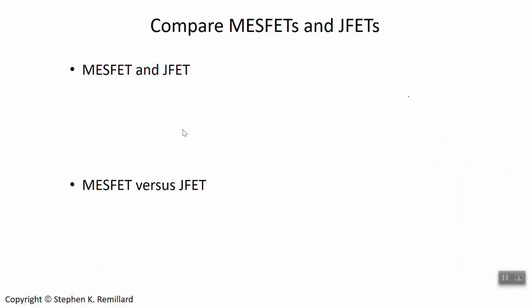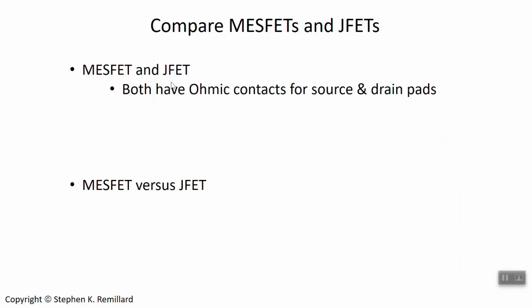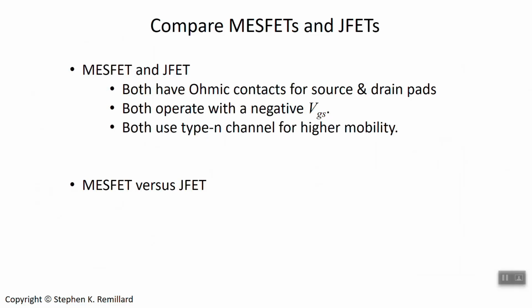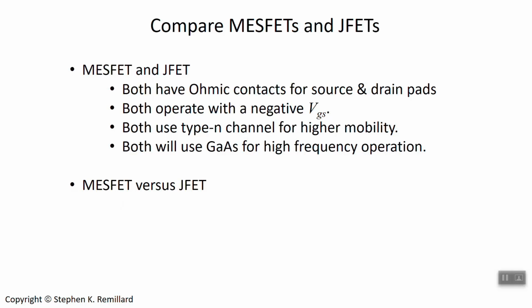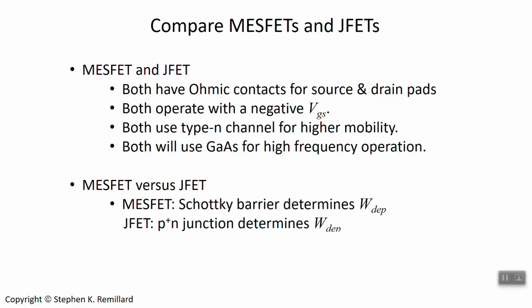Let's compare MESFET and Jfet. First, let's see what they have in common, and then we'll see what's different. They both have ohmic contacts for source and drain pads. Okay, low-hanging fruit there. They both operate with a negative gate voltage. They both use a type N channel because you really want the high mobility for high speed. And they both usually use gallium arsenide for that same reason, to get the high mobility so you can have high-frequency operation. They're different in that the Jfet was an actual PN junction, and that's what determined the depletion thickness, as opposed to the MESFET, where it's a Schottky barrier diode that determines the depletion thickness.